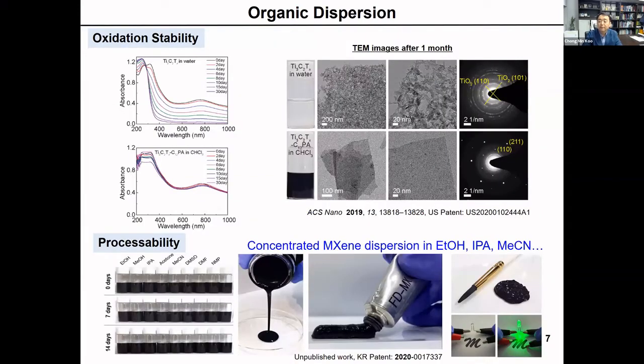The organic dispersion reveals very strong oxidation stability, as Yuri's group mentioned. Since the organic dispersion can exclude water and oxygen, it can extend the storage time without degradation. Additionally, this organic dispersion with non-toxic organic solvents provides better solution processability, even for coating on hydrophobic substrates.